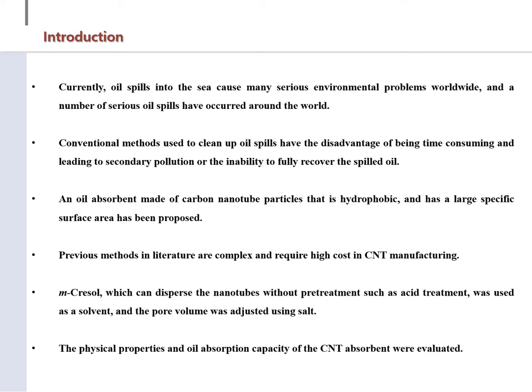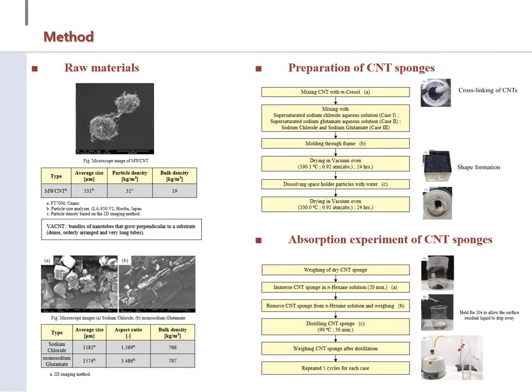In this study, a preparation method of the CNT oil absorbent is proposed. The method was characterized by forming shape and increasing density of the CNT using metacresol as processing solvent, and by increasing the inner macro and meso pores inside the absorbent using salt. The CNT was prepared by mixing of commercial multi-walled CNTs, metacresol, and salts such as sodium chloride and sodium glutamate. They are molded in a frame and dried. Then, salt is dissolved in water and finally the absorbent was produced after drying.